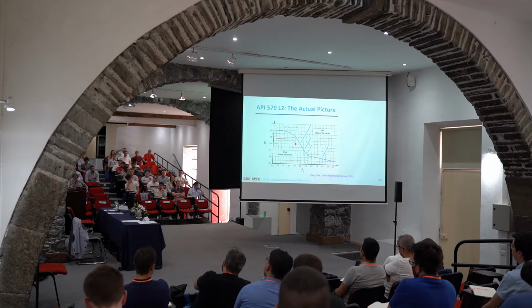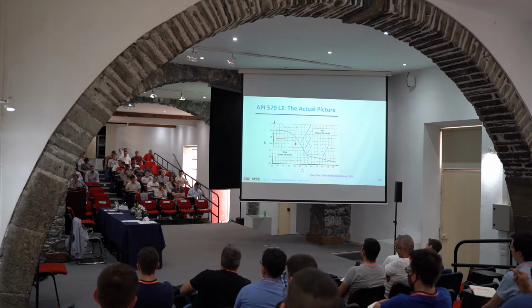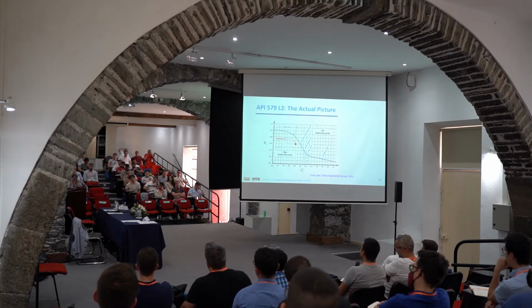If it's below the curve, it's safe. If it's outside the curve, it's not safe. Then you need to take measures. For example, in this very simple example that I just gave you, and that's very common in the petrochemical industry, somebody finds a crack in, let's say, a heat exchanger or pressure vessel, and the petrochemical industry cannot stop. Those guys work 24/7, 24 hours, seven days a week, unless it's scheduled maintenance. If they find a crack and the assessment shows it's a little bit unsafe, what they do is reduce the pressure. That's the easiest way. They just reduce the pressure and keep moving.